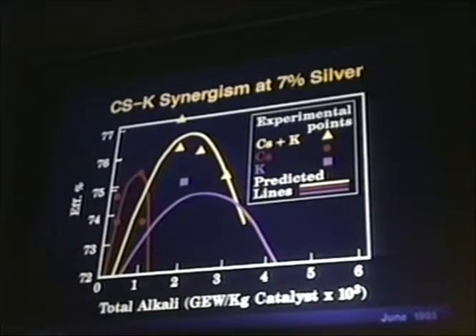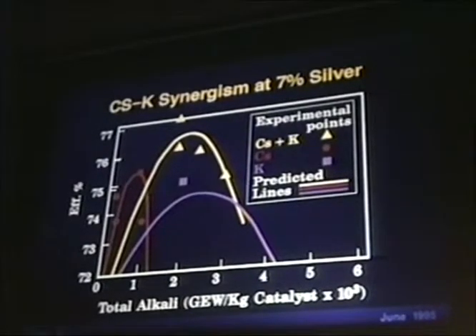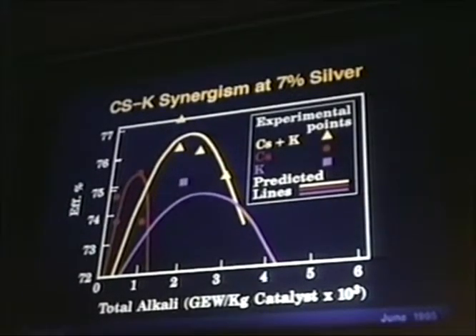The efficiency for the cesium-potassium mixture, as you can see, is not only higher by a percent, but broad in response to alkali. And as you can imagine, a broad optimum is more desirable than a very sharp, narrow optimum. This is indeed an added beneficial feature of the mixed alkali system. Now, the question I couldn't answer at the Budapest International Congress, I would attempt to answer today. That is the mechanism of synergistic alkali promotion. I'll share with you the likely cause or causes.